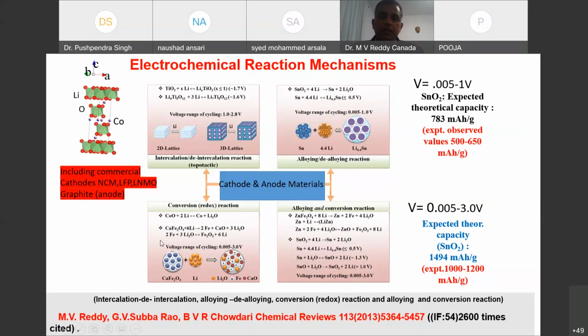So another thing is the conversion. Again, these are a little bit technical and academic. Sometimes the challenge in this type of oxide is how to reduce the voltage. Although we get some high capacity, practically sometimes we cannot use it because we don't have any proper matching cathodes and there is some problem with voltage hysteresis, etc. So again, for example, alloy means depending on the voltage, in the same material we can see the conversion also. So again, we can get some high capacity, but there are other limitations, especially voltage, etc., that we take into consideration.